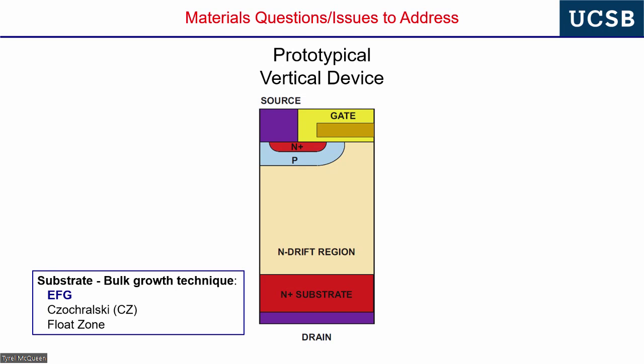Now comes a semiconductor, beta gallium oxide, that has melt-grown substrates. And these substrates, they're not as good as silicon or germanium substrates, but they're not far off the quality of gallium arsenide substrates or indium phosphide substrates or gallium phosphide substrates. And this has enabled an incredible pace of the field. So if you have native gallium oxide substrates, it'll go very fast, and you'll find out if it looks good as a semiconductor or not. But you won't be plagued by heteroepitaxy on foreign substrates. That really slowed the progress in gallium nitride. I think the field would have gone much, much faster if there had been a breakthrough in substrates and they were widely available.